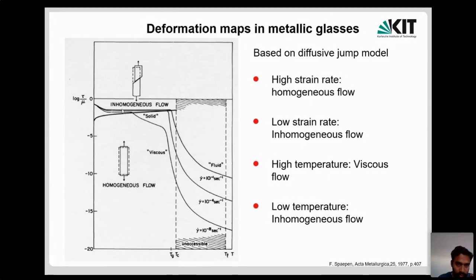And if you see the strain rate sensitivity at room temperature, it's practically strain rate insensitive, because at 10 to the power minus 1, minus 4, minus 8, these are like 7 orders of magnitude, and the stress change is very minimal at room temperature. So this is generally the behavior of glasses. And this is again based on the diffusive jump model, which I told you, the second model, which was not very popular. However, this is a very easy model to do some calculations, because the model is based on diffusion. That's why.